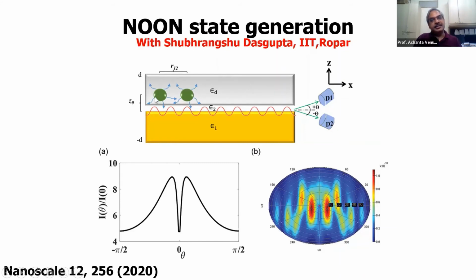But the main point is that quantum dot 1 and quantum dot 2 are coupled via this plasmon mode. Because of this coupling, if you measure the photons, each one emitting a photon out, these are highly directional. First, they come in two lobes, two different directions, and all the photons are either in detector 1 or in detector 2. It's not that one photon goes to D1 and one photon goes to D2. That's because of this coupling. If the coupling is made zero, then they can come in all directions: both in D1, both in D2, or one in D1 and one in D2. All these combinations are possible. But because of this coupling, we can generate these states where all the photons go preferentially to one or the other direction.